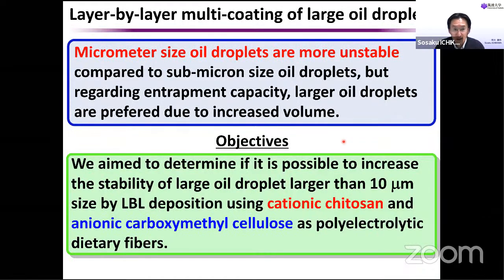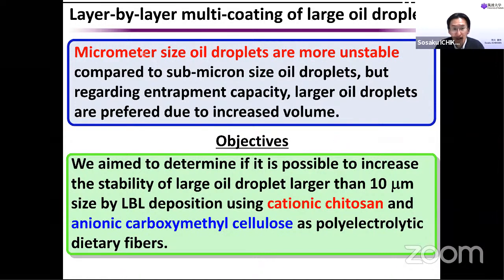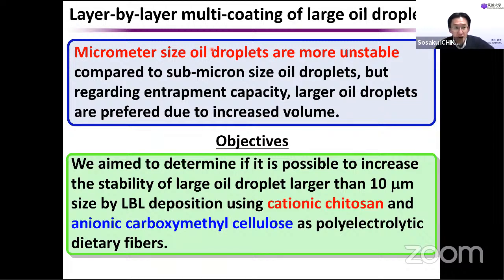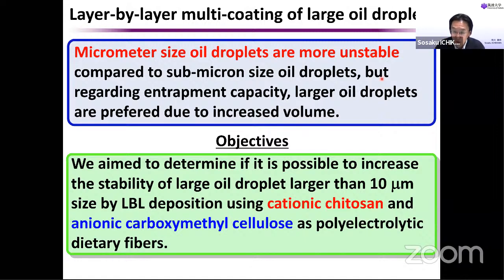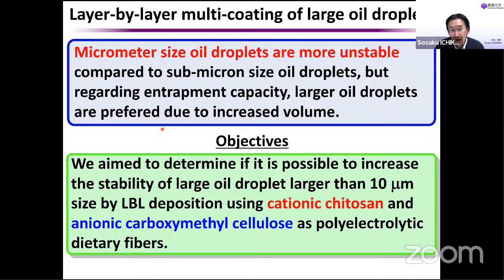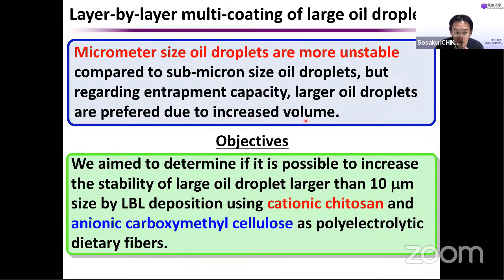So we focus on the very large oil droplets in the micrometer size because the very large oil droplet is unstable compared to the submicron size of oil droplet. But regarding the entrapment capacity, large oil droplets are preferred due to the increased volume. So we aim to determine if it's possible to increase the stability of large oil droplet larger than 10 micrometer size by this layer by layer deposition using cationic chitosan as a polymer and anionic carboxymethyl cellulose as polyelectrolytic dietary fibers.